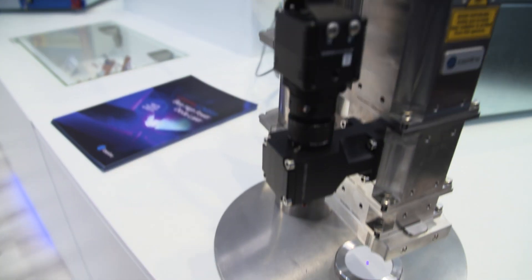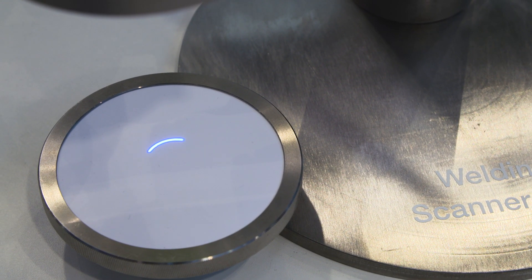Laser Line relies on the blue laser. The blue diode laser is continuous emission with 1.5 kilowatts of power. With the blue diode laser, they can now achieve absorptions of more than 50%, for the first time enabling very good controllability of the energy input and also controlling the heat input, driving processes that were not possible before, especially for e-mobility.